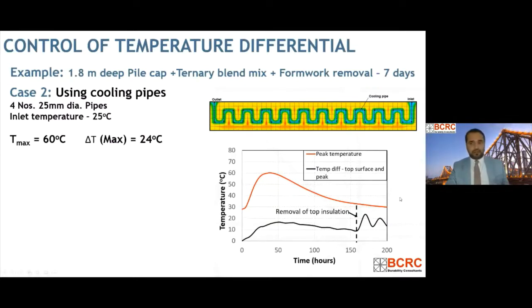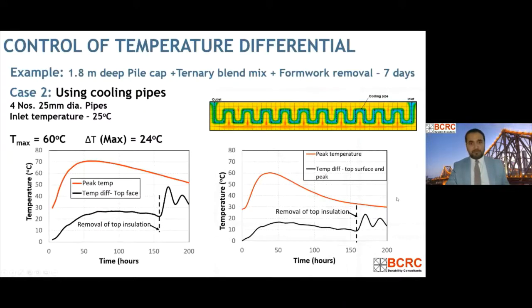So just to make a comparison with the previous example where we have done modeling without any cooling tubes, you can see that we have not only reduced the peak temperature, but we also have increased the rate of cooling in the cooling phase, which is very helpful in keeping the temperature differential within the allowable limits, right?